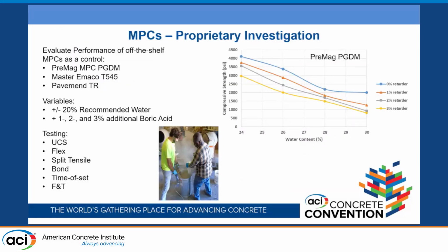So this is the proprietary material investigation. We started out with 3 proprietary materials. We got a material from Premier Magnesia, Master Emaco T545, and then Pavemend TR. And we took the 3, we tested them all at design, and then we did 20% above design, 20% below design, and also with water and with boric acid, and varied it. We did a whole host of testing, and the main takeaway here is that this is your water content going up,